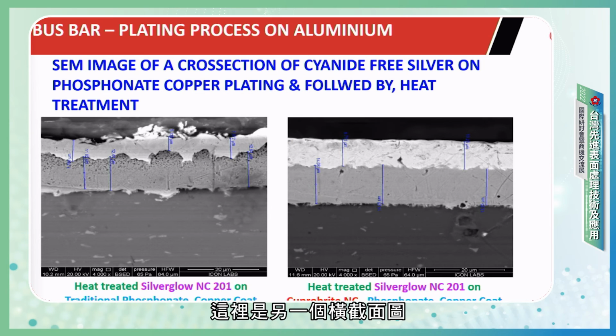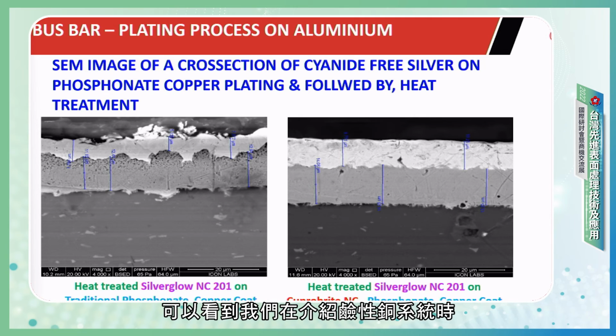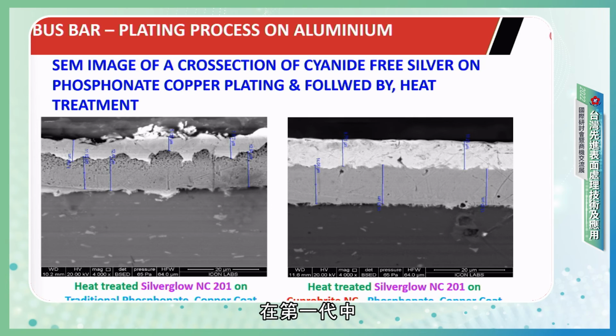Here, what we have done is another cross-section figure. Here we have silver, and this is the copper. You can see the comparison of what we discussed in the very first slide, when we introduced our alkaline copper system containing the second generation with mixed phosphonates. You can see in case of first generation, there is a rupture in the coating of non-cyanide copper, whereas with the second generation coat, you don't see such rupture.